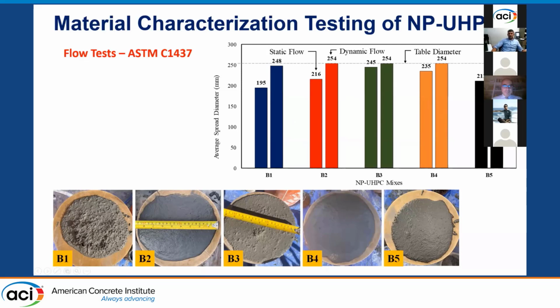But you can see that there's some variation in the flow, which is expected. We see that this might have the lowest flowability, but it's still acceptable and you can furnish it in a field joint. So our target here is to meet the minimum required flow as well as other mechanical properties. Flow is not mechanical, if you can argue, but flow and other mechanical properties as well. So that was our target here. They have the most practical, convenient mix that can work for this type of joints.